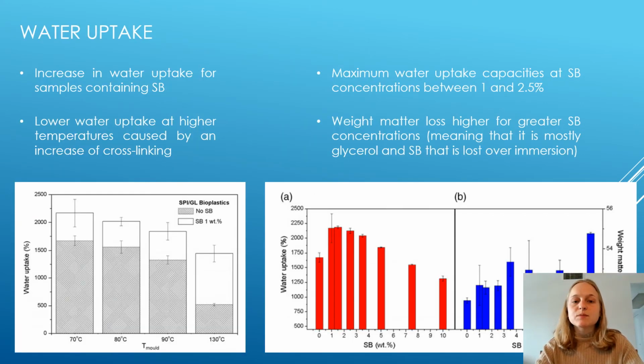For the water uptake experiments, we can see that an increase in temperatures resulted in lower water uptake for all the samples, which can be explained by the increase in cross-linking at high temperatures, leading to a more packed structure less prone to absorbing water. However, the water uptake greatly increases for samples containing SB, which peaks at around 1 to 2.5%, which also corresponds to the highest values found for maximum strain. However, after that, it diminishes progressively.